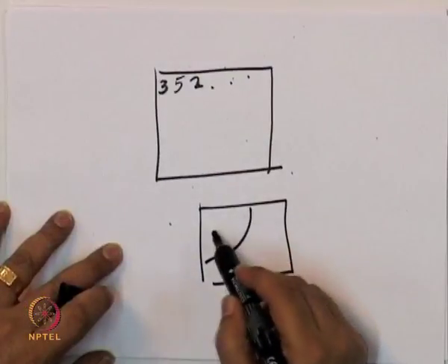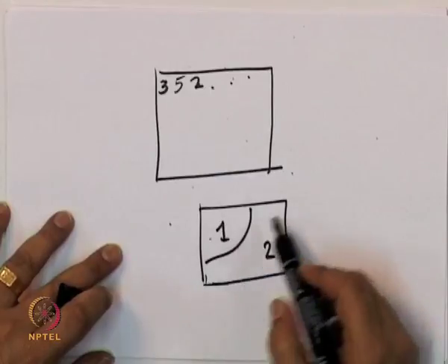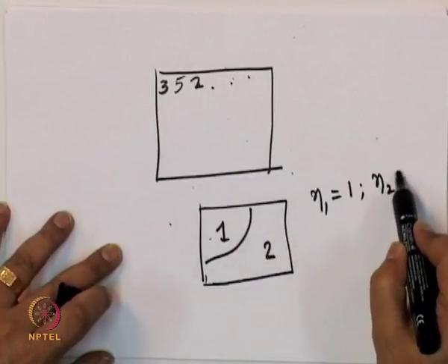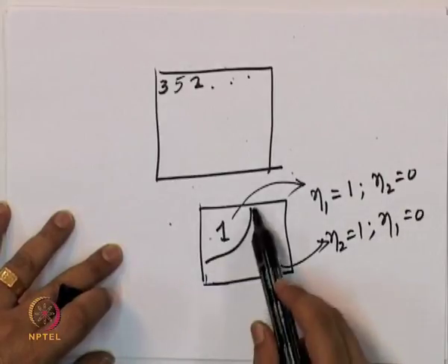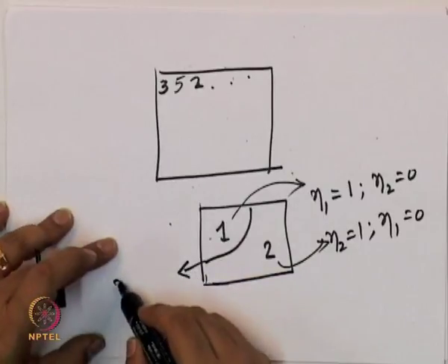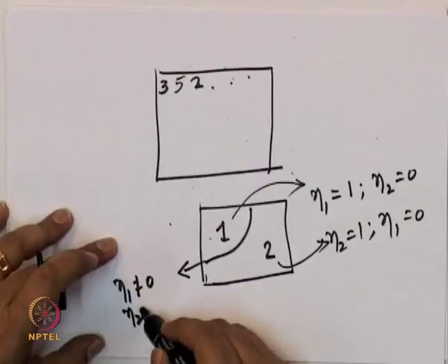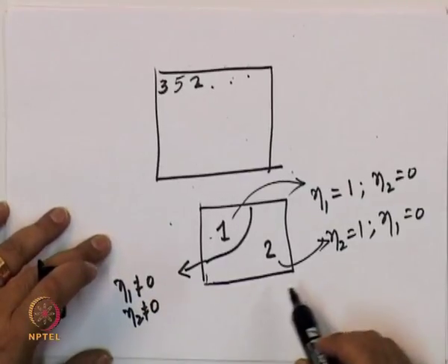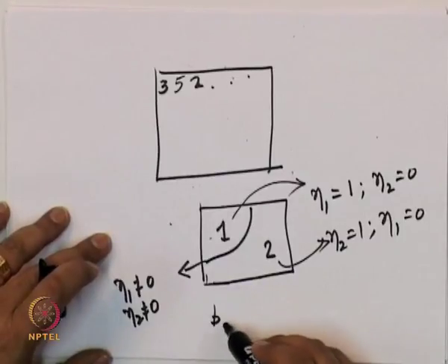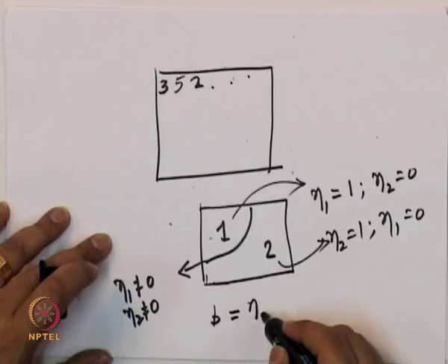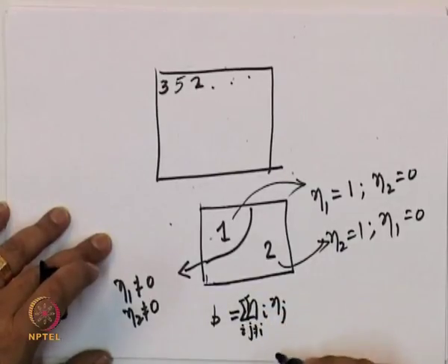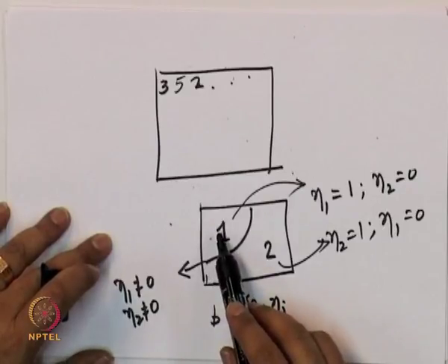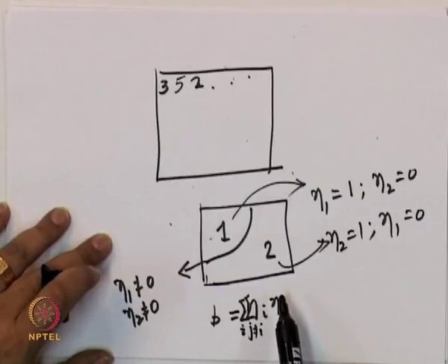So, we said that let us look at this grain structure. Suppose I have a grain like this and a grain like this, I said that eta 1 will be equal to 1, eta 2 will be 0 in this region, and in this region eta 2 will be 1, eta 1 will be 0, and in the boundary region both eta 1 is not equal to 0 and eta 2 is not equal to 0. So, I am going to define a function called the boundary function, and this function is basically eta i eta j, a double summation over i and another summation over j not equal to i. Now, as you can see, in the bulk all the other etas are 0, so that is always going to give 0,